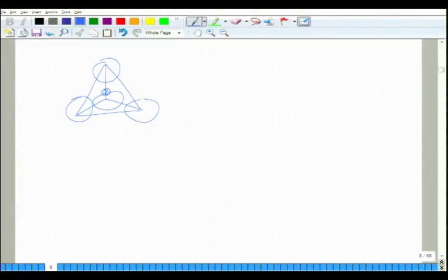If you remember we worked out 2 distances CV and CF, okay. So, you just have to work out this distance from center to center. So, this distance, let us say if this is A, this is B, AB is equal to R plus R tet. So, you need to work out AB in terms of small r using the geometrical methods of a simple tetrahedron. So, this will again give you the same relation.